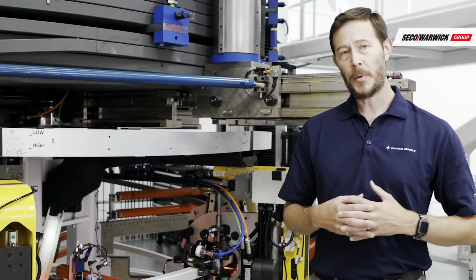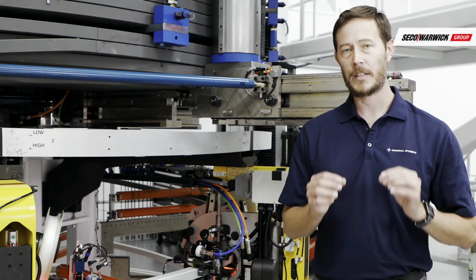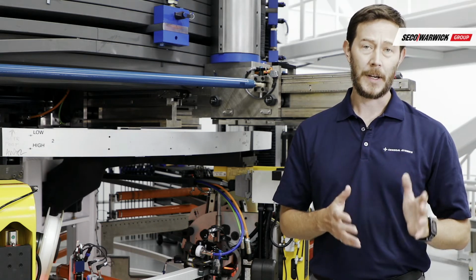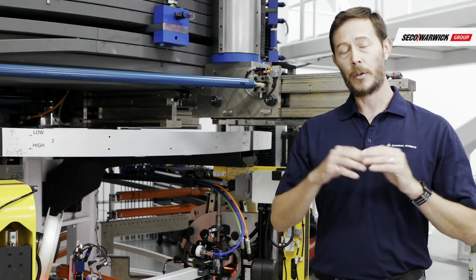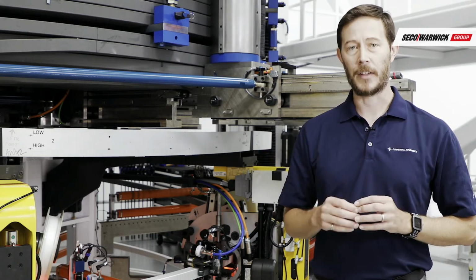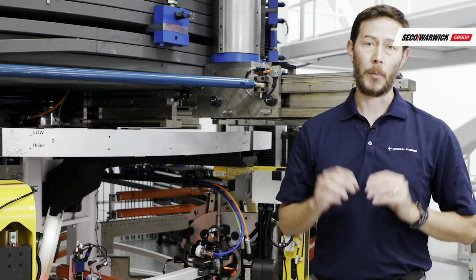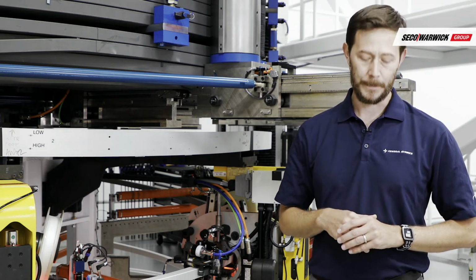A 5 weeks long heat treatment process is very unusual for most of our viewers. But what about process requirements and temperature uniformity within 6 kilometers of conductor? The temperature inside the furnace has to be ramped very slowly and controlled at 5 degrees C per hour. And the uniformity of the module is watched very carefully. No two spots in the module are more than 20 degrees Celsius apart from each other.